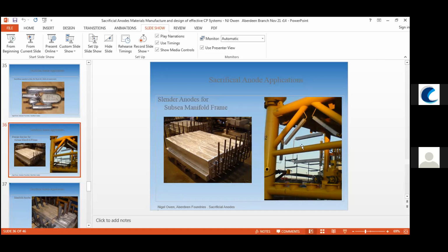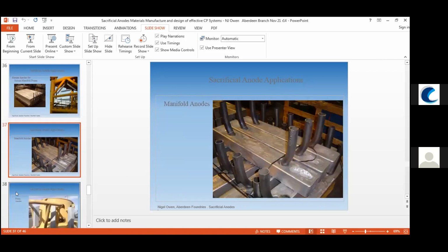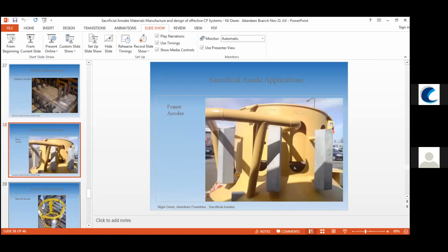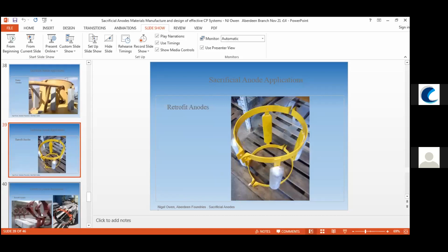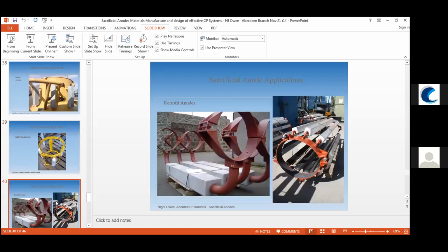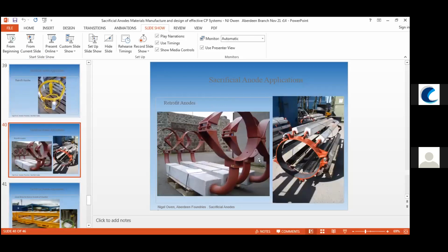which, if we just run down here, you'll see that these are basically retrofits. In other words, once your first lot of anodes have run out, you've got to put some more on. Well, your pipeline might be under the water in a trench, and it's going to need anodes too. You can put these around the tubulars adjacent to, or swap out and cut off the old anodes. But they have additional steelwork in order to facilitate this.